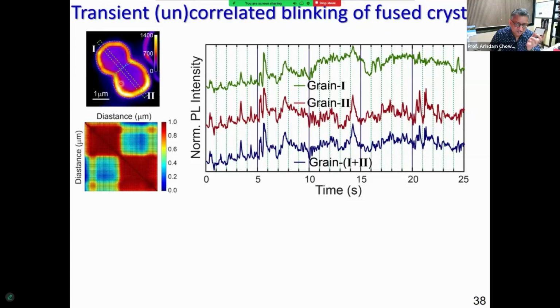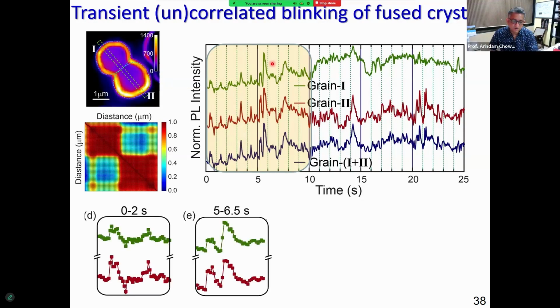And if I look at a trajectory, the intensity of grain 1 and grain 2, I would like you to only look at the green and the red curves that are shown over here. X-axis is time, y-axis is PL intensity. You will notice that in a certain region, up to 10 seconds, there's a clear correlation of the blinking between the two grains. Of course, these are just blow-ups to show you that these correlation events exist. But beyond 10 seconds, from 10 to 25 seconds, this correlation seems to be lost.